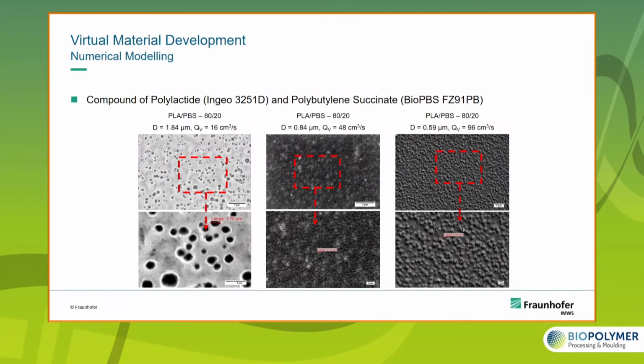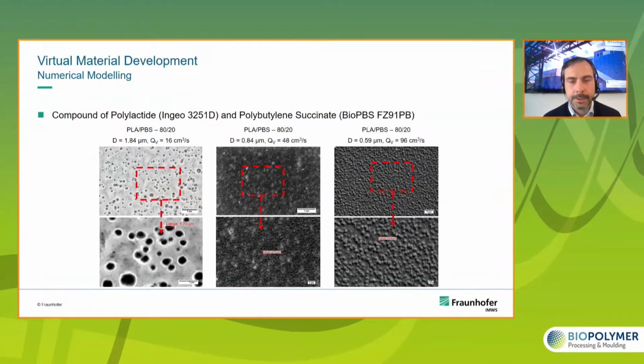So what you can see here are the pictures of the scanning electron microscopy of the microstructure of the blend of PLA and PBS with a composition of 80% PLA and 20% PBS. You can see on the left side the microstructure for a flow rate of 16 cubic centimeters per second, in the middle of 48 cubic centimeters per second, and on the right of 96 cubic centimeters per second. And you can clearly see that with increasing flow rate, we have a decrease in the particle diameter.